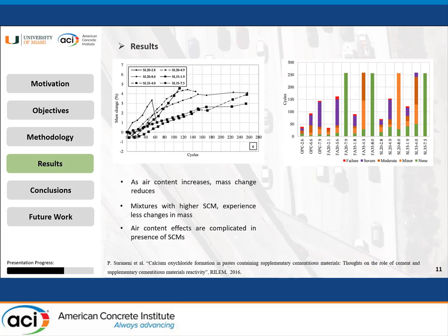And as you can see over here, we have our visual assessment classification. So the ones having the red color at the tip of the bars, it means that they have already failed. The ones with the green color have not experienced any sign of damage. So the mixtures with no entrained air are failing at very early ages. As you can see, the ones with no entrained air, this one here, this one here, and this one here, have already failed at very early stages.